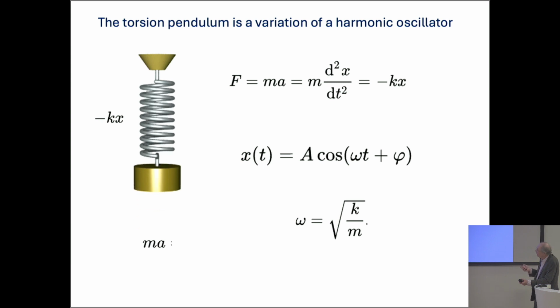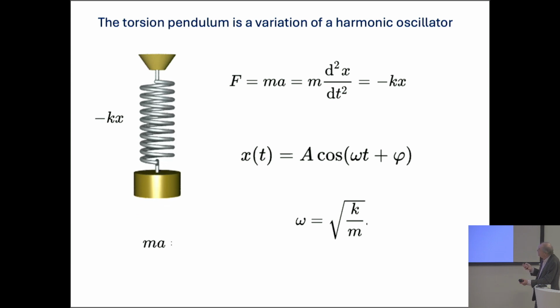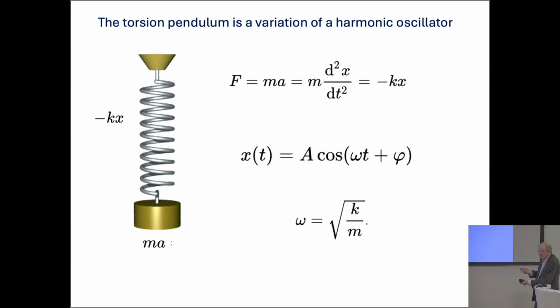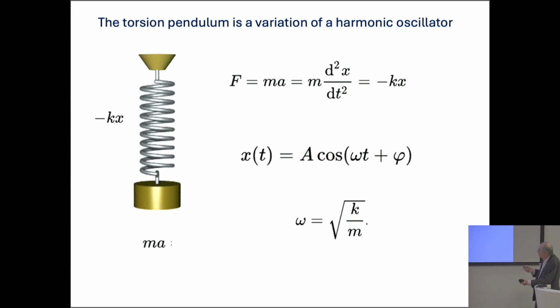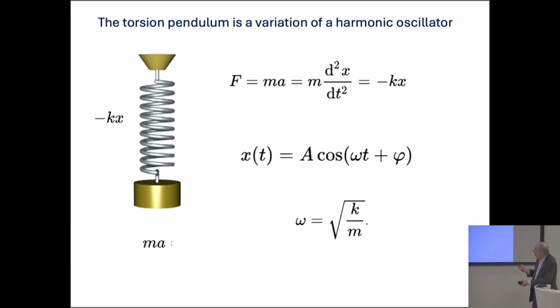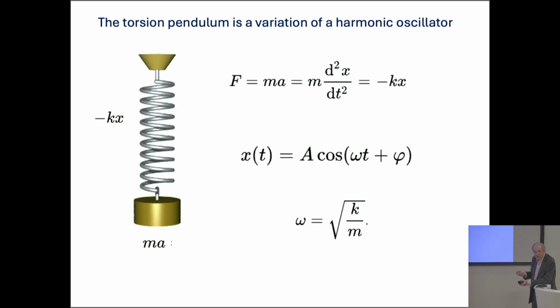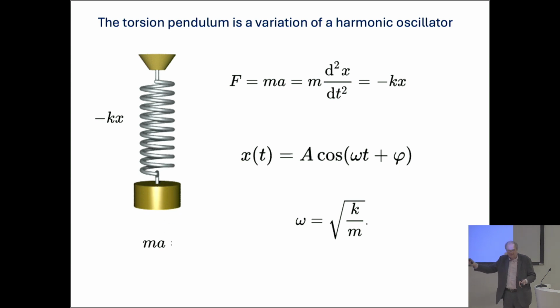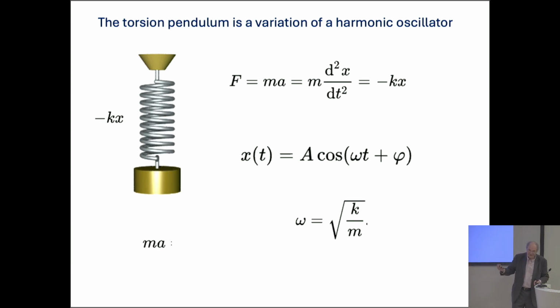The useful thing is that the frequency of the oscillation gives you a way to measure the spring constant, K. The frequency is the square root of the spring constant divided by the mass. The mass you know; the spring constant typically you don't know but want to measure. This is the elastic modulus of the tissue to some extent. That's the idea.